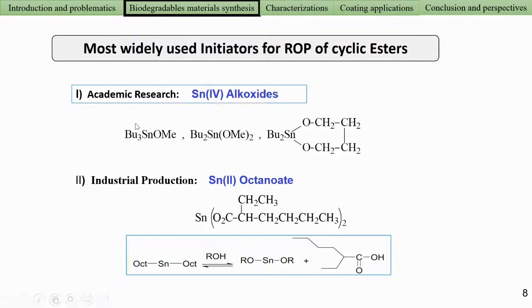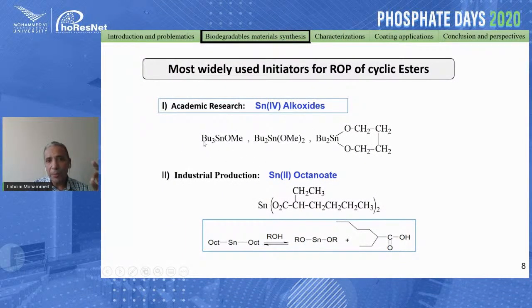But all these complexes, even if they are excellent catalysts, cannot be used in industry because of the tin-carbon bond, which is really toxic. The standard catalyst for ring-opening polymerization and other technical production, for example of polyurethane, is based on tin octanoate, because this compound is admitted by the American Food and Drug Administration as a food stabilizer. But for some reactions, or to increase its activity, we have to use an alcohol as co-initiator. The alcohol can act as a transfer agent during the polymerization, and consequently we lose the control of the polymerization, which is required to have a really good polymer with specific properties.